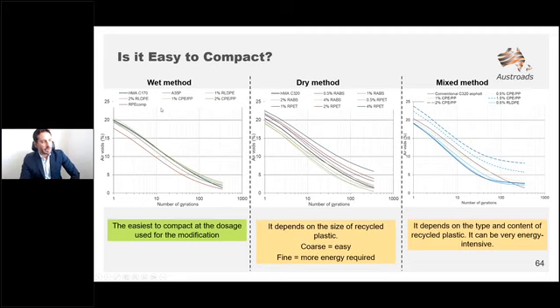Keep in mind that we only pushed this up to 2% of recycled plastics. Higher content may require the addition of chemicals to stabilize the system. So together with the advisory board, we decided not to go to higher percentages. And this is definitely the easiest to compact at the dosage used for the modification. The dry method was basically affected by the size of the material used. The dotted lines are related to the coarser fraction of the aggregates we replaced with the natural aggregates, and the solid lines are related to the fine fraction of PET that we used as a partial replacement of sand particles. In the mixed method, that's the one we'll be looking at today.